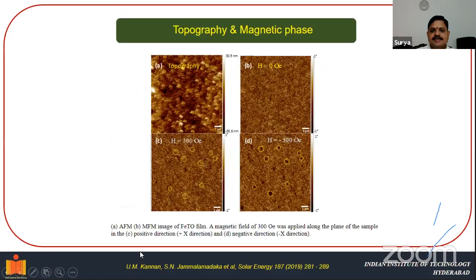Okay, so let's see what kind of images we have obtained. For instance, consider this is the topography image that we have obtained from the magnetic force microscopy, and this is H equal to 0. That means initially we don't apply any magnetic field to the film. As a result, we don't see any magnetic phase image. Okay, now to observe